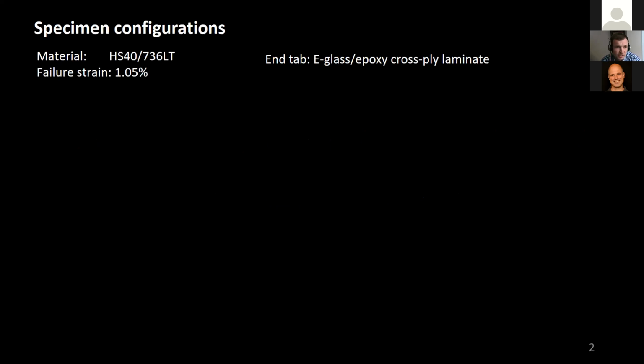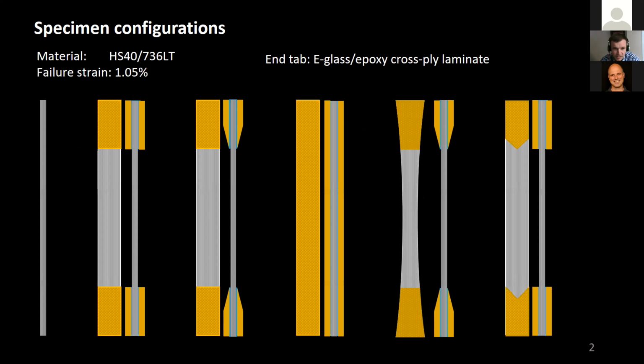So we did a range of tensile tests on UD composites, and here we used HS40, which is a relatively brittle carbon fiber with a failure strain of 1.05% according to the data sheet and a stiffness of 455 gigapascal. We put end tabs on this, and this is just standard E-glass/epoxy cross-ply laminates. And we did 6 different configurations, which are schematically shown here.